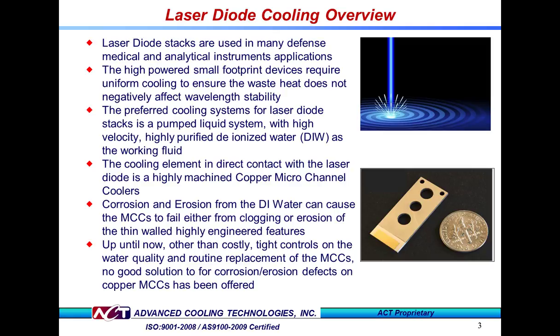Water that has dissolved oxygen and pH values that are too high or too low can enable the formation of particulates that block MCC passages, thereby reducing the thermal performance of the cooler. The cooling element that is in contact with the laser diode is a complex, multi-level copper microchannel cooler. A sample copper microchannel cooler can be seen on the lower right.